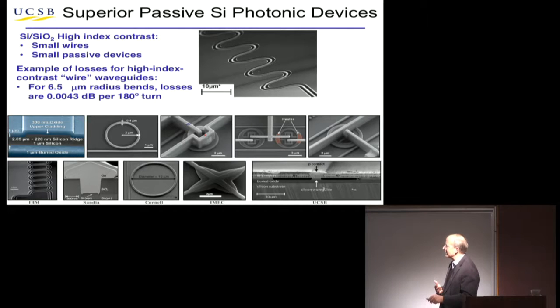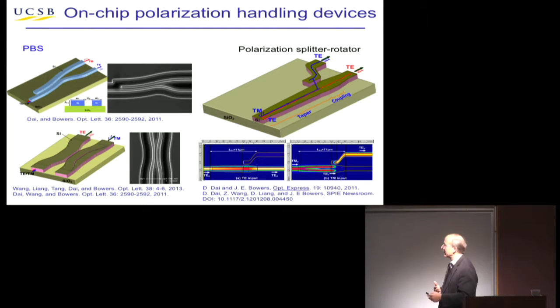And again, here's some of the different things that people make. These are typically heaters for ring resonators. But again, the good process control in silicon photonics makes that all possible. Some of the devices we've been working on, for instance, are passive devices, polarization beam splitters or polarization rotators and splitters. And the performance depends very much on details of the width, right? So the curvature here matters, the gap matters. A lot of times the gap is changing along the length, the width is changing along the length, so as to get the property you want.